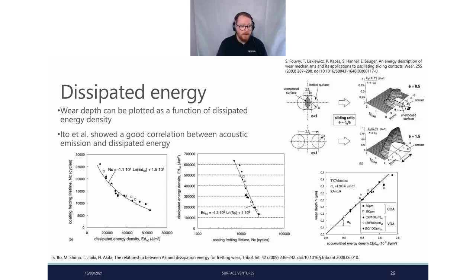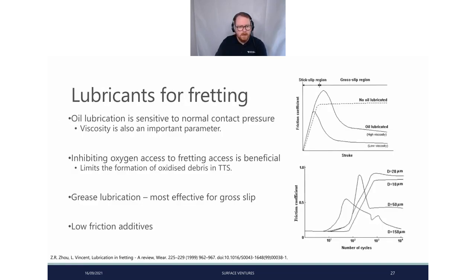And then another paper by Ito et al. showed that we have a quite good correlation between acoustic emission and dissipated energy in fretting. So another technique that we can use to measure this. So moving on, as I said, lubricants for fretting.